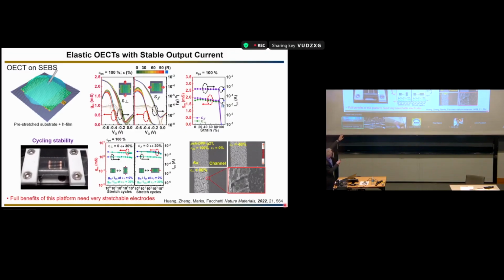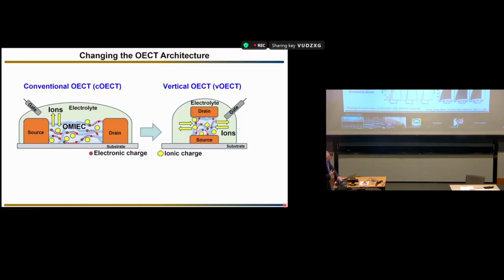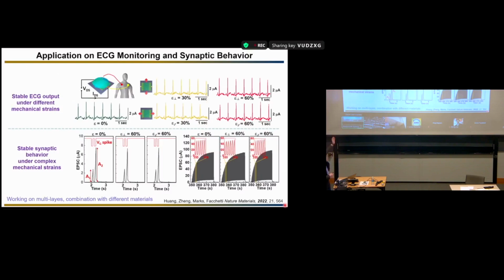What is interesting is that for this type of device, the limitation is that you start getting failure not because the semiconductor is cracking, but because the electrical contacts start cracking. So if you have some clever way to integrate this honeycomb with contacts which are much more ductile, this would make an impact. And it's not easy. I've been trying to do it. It's very difficult. So if you have some idea, please let me know. I can give you the honeycomb film, and then we can integrate and do some physiological sensors.